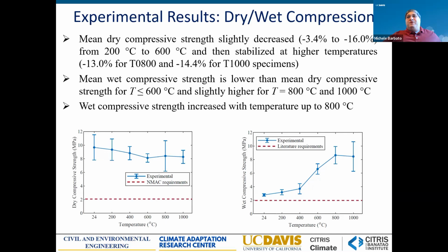However, for the wet compressive strength, and this was a little bit more surprising, although in hindsight it made really good sense, we found that the strength is increasing actually significantly. We went from about 2.5 to almost 8 megapascal of wet compressive strength. And that is because we are fundamentally with fire transforming our unfired clay blocks into fired clay blocks, which are known to be equally resistant under wet conditions. So the material actually got stronger.